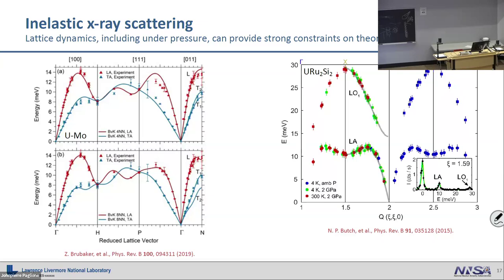This is an example of something we did 10 years ago, this experiment, I guess, on uranium ruthenium two silicon two. So if you haven't heard of that, don't ever look it up and don't work on it. But you can get some good phonon measurements. And these were done at 2 GPa. And this was a very difficult, very time-consuming measurement, especially to get green and blue and everything to overlap. But it's a really powerful tool.